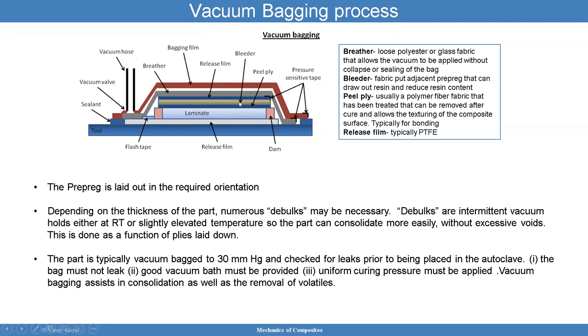The bleeder is a fabric that's put adjacent to the prepreg, and that allows you to draw excess resin out and reduce resin content. So you don't want to have a prepreg that has too much resin, because that means that you have too much resin content. You want a good balance. You don't want voids, and you want the right amount of resin. So the bleeder just takes the excess.